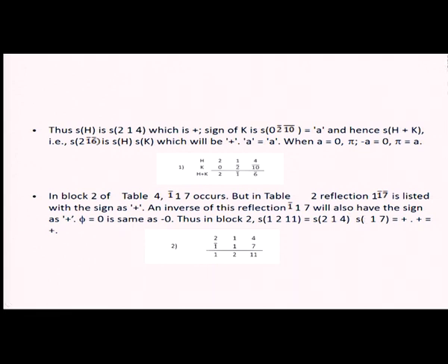Okay. Now, let us see what is the sign of 1 bar 1 7. We have the reflection 1 1 bar 7 bar as plus. If you take the inverse, that is minus minus of everything, from this I get 1 bar 1 7, because it is plus, it is going to be plus also for the inverse, that is what I told you. If a reflection has a sign or phase 0 or pi, sign plus or minus, the inverse reflection will also give the same sign.